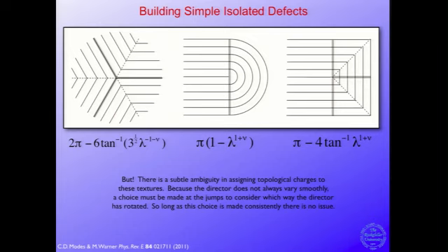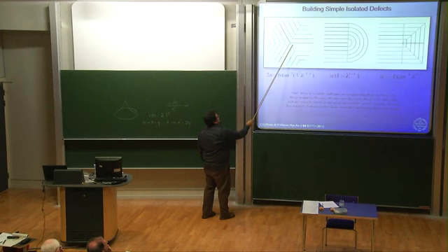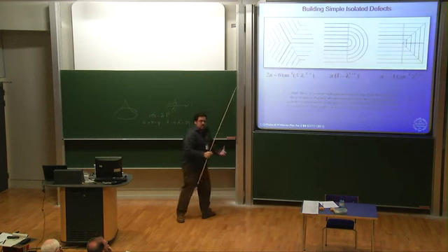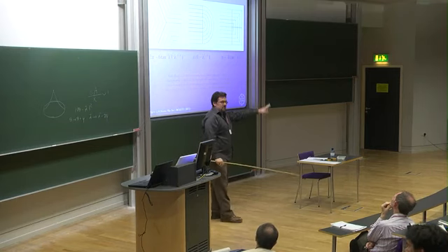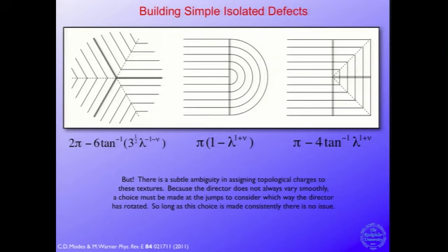And you can calculate, so remember we had all those simple equations for the change in the angular opening. Once these wedges have been put together, there's no longer an angle to open, right? You've got a continuous piece of flat space there. And if you add up all the angle changes, you get a total angular deficit or surplus.